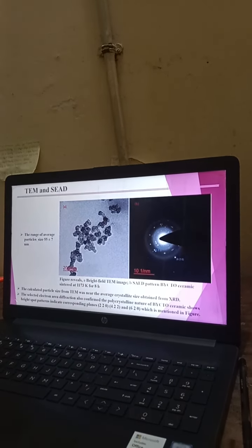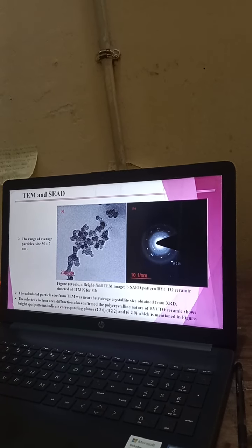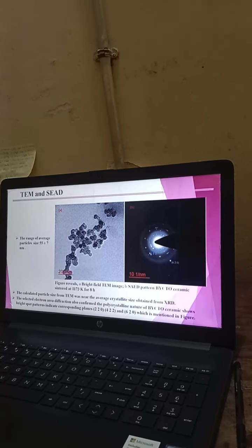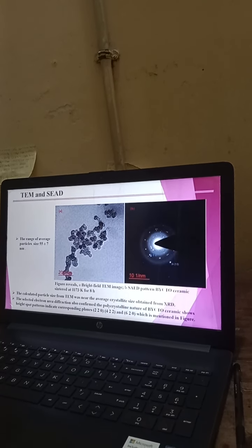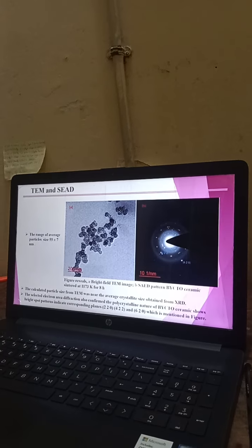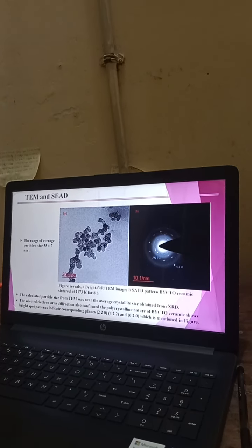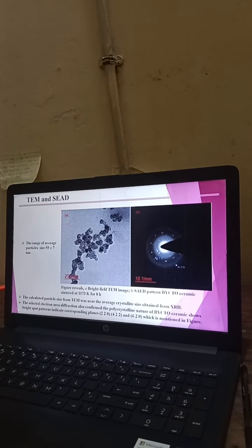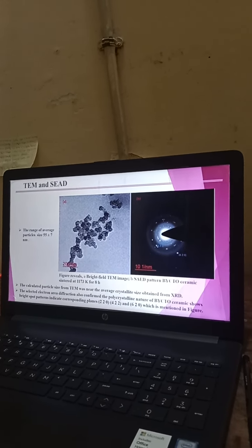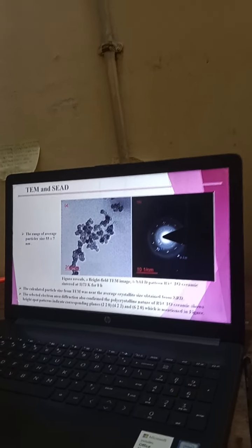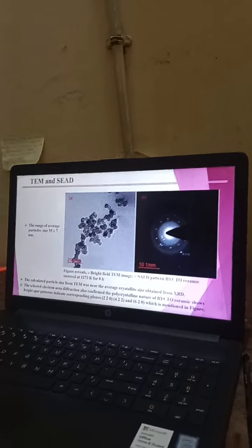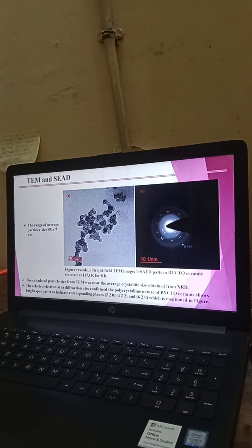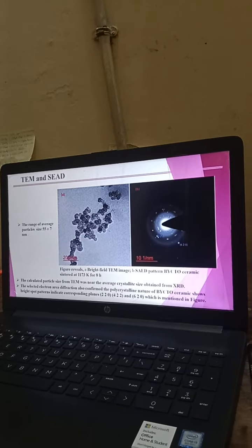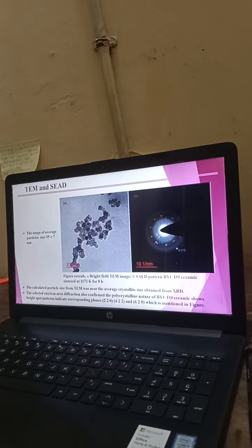TEM and SAED. Figure A shows the TEM image of the BYCTO ceramics, and figure B shows the SAED pattern of the BYCTO ceramics sintered at 900 degrees centigrade for 8 hours. In figure A, the particles look nearly spherical, and each particle has a different particle size. The average particle size was calculated by ImageJ software and found to be in the range of 55 plus minus 7 nanometers.